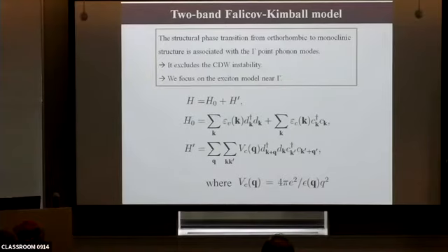The tantalum nickel selenide shows a structural phase transition from orthorhombic to monoclinic upon cooling, and this structural phase transition is associated with the gamma point phonon mode only. So it excludes the CDW transition. Therefore, we focus on the excitonic model near the gamma point.